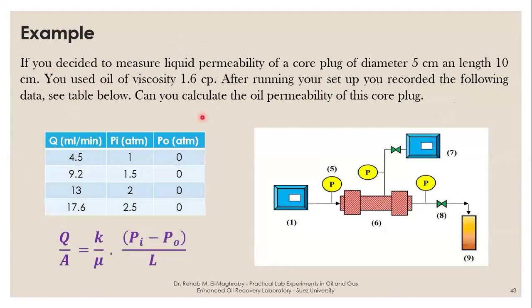So this is an example of what we can measure here. You have a core plug with a diameter of 5 centimeters and a length of 10 centimeters. You have the viscosity, 1.6 centipoise. After running, you have measurements at different flow rates, and according to the change in the flow rate you have a different inlet pressure, and the outlet pressure is zero actually. It's atmospheric.